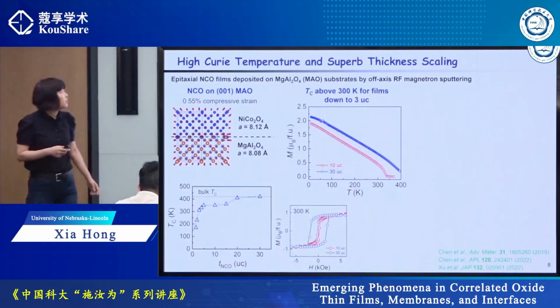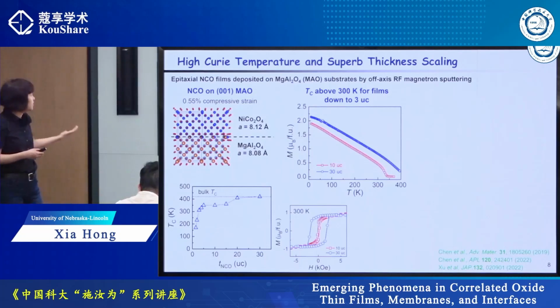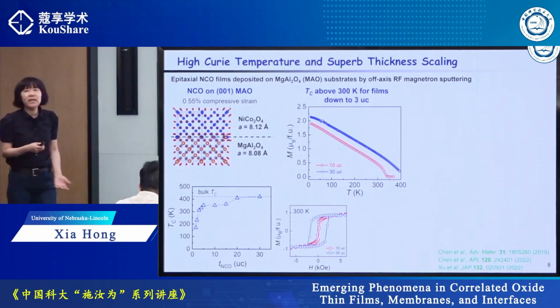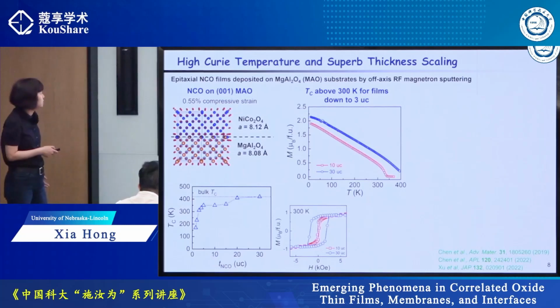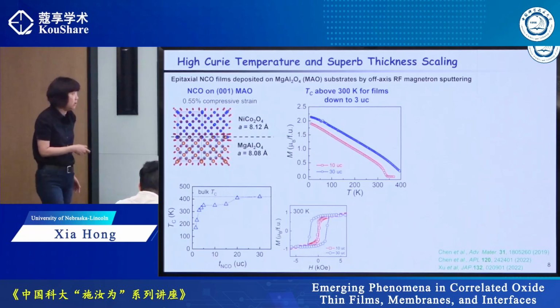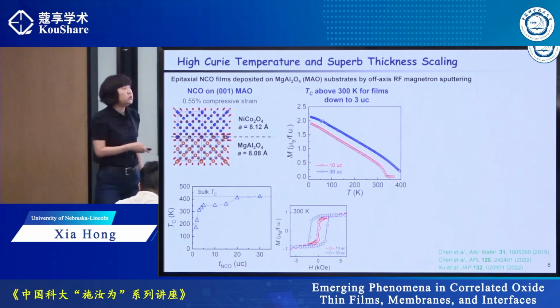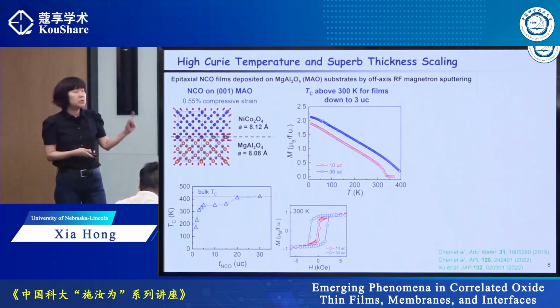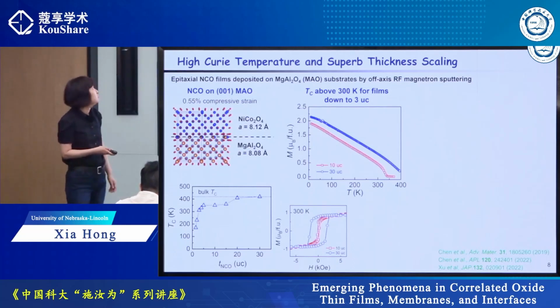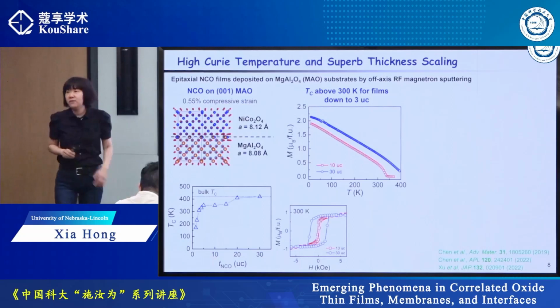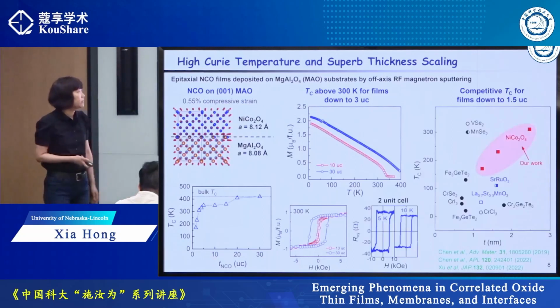And with the metal-insulator transition, you can see the magnetic order also gets suppressed. So you can see with the reducing film thickness, Curie temperature is lower. But we managed to have above room temperature Curie temperature, even down to 3 unit cells. And the material shows very good perpendicular magnetic anisotropy when it's grown in the 001 phase. So that is a compressive strain.